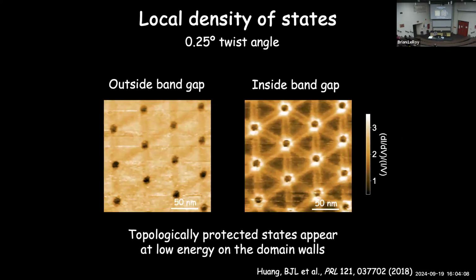So if I now look spatially at this, if I look at an energy above the band gap, so at a high energy, I have pretty much uniform density of states. Again, the color scale is density of states. White or orange is high, black is low. These dots here are these AA sites, which I said we're going to ignore. But other than them, it's pretty much a uniform density of states. The electrons are happy to go wherever you want.